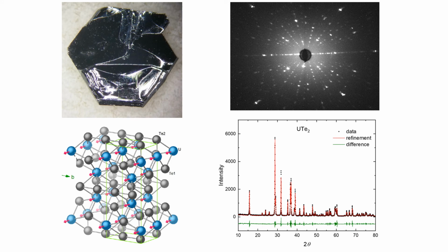Well, as you can see, I got very nice single crystals, very nice X-ray diffraction pattern, but what was known about this compound? It turns out uranium-tellurium-2 has been studied for decades. This is a summary of what was known by 2006. Single crystals can be synthesized, resistance, magnetization, specific heat were carried out down to 2 K. It is just another heavy fermion compound with no magnetic ordering.